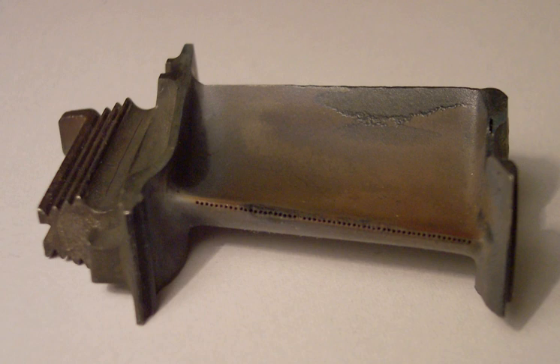Ni-based superalloys at lower temperatures. It is body-centered tetragonal, BCT, and the phase precipitates as 60 nanometer by 10 nanometer discs with the 001 planes in gamma double prime parallel to the 001 family in gamma. These anisotropic discs form as a result of lattice mismatch between the BCT precipitate and the FCC matrix. This lattice mismatch leads to high coherency strains which, together with order hardening, comprise the primary strengthening mechanisms. The gamma double prime phase is unstable above approximately 650 degrees Celsius.